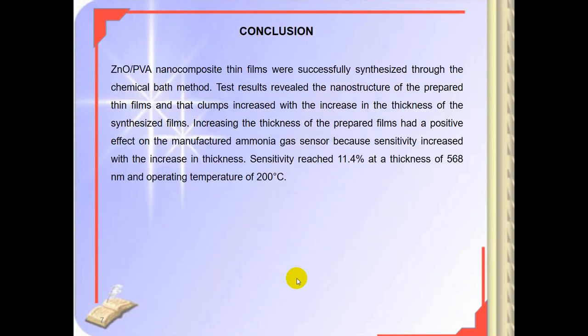nanocomposite thin film. Conclusion: ZnO-PVA nanocomposite thin films were successfully synthesized by chemical bath deposition. Test results reported the nanocomposite structure of the prepared thin film, and the clumps increased with the increase in the thickness of the synthesized film. An increase in the thickness of the prepared film had a positive effect on the manufactured ammonia gas sensor because sensitivity increased with increase in the thickness. Sensitivity reached 11.4% at the thickness of 568 nanometers and operating temperature of 200 centigrade.